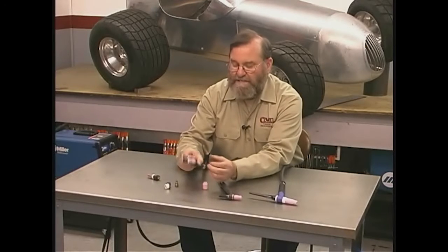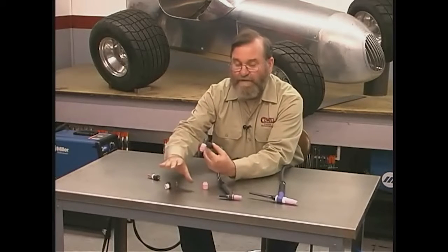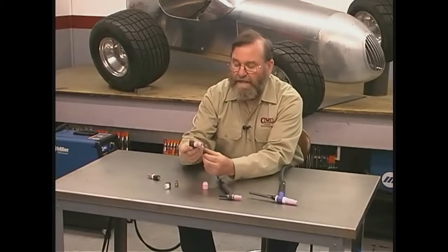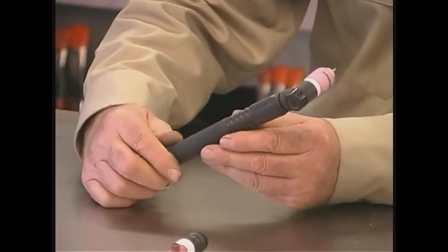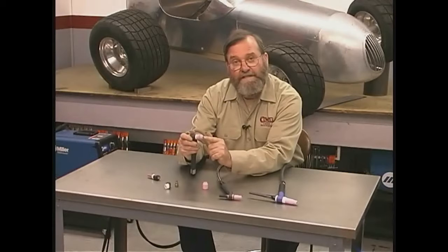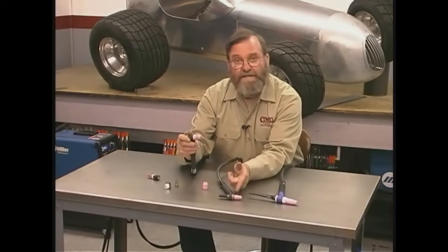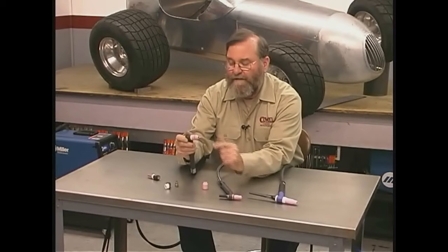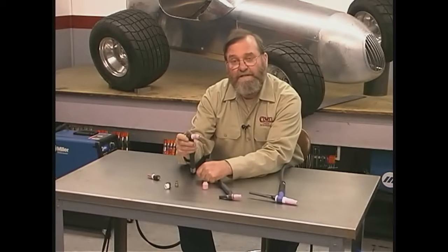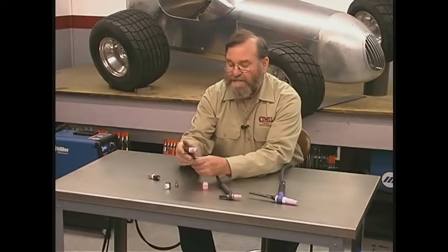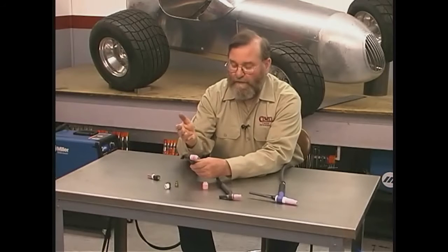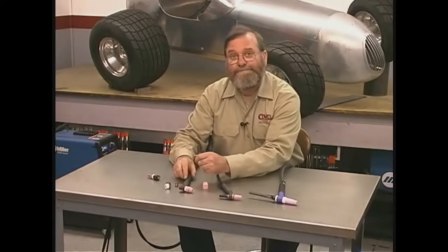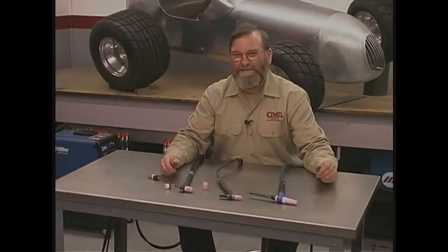And one of the advantages of using a gas lens is it does give you better gas coverage of the weld area, but also you can stick the tungsten out a little bit farther if you need to. If we stuck the tungsten out this far with a traditional cup, it wouldn't work. We wouldn't have a sufficient shield around the tungsten to do good welding. So those are some of the varieties that are available with TIG torches. Next thing we'll do is talk about the bewildering array of tungstens that are available for the torch.